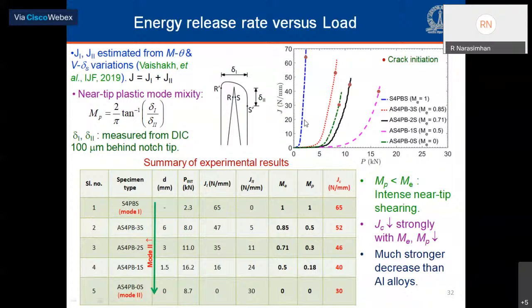As we go towards mode 2, the specimen experiences larger levels of load. The crack initiation stage is indicated here by the dots. These key results are summarized in the table here. We also introduce here a definition of plastic mixity, MP, based on measured values of near tip opening and sliding displacements of the crack tip, which is indicated by the equation on the left side.